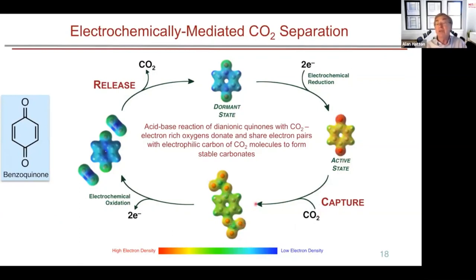So this is a way in which we can then modulate, control the capture of the CO2 by controlling the electronic distribution on the molecules by reduction. And then when these are fully loaded, we can regenerate them by oxidizing these again, removing those electrons, going back to the dormant state, which has no particular affinity for CO2 whatsoever, and we can release the CO2 in a flash tank, and then recycle these systems.